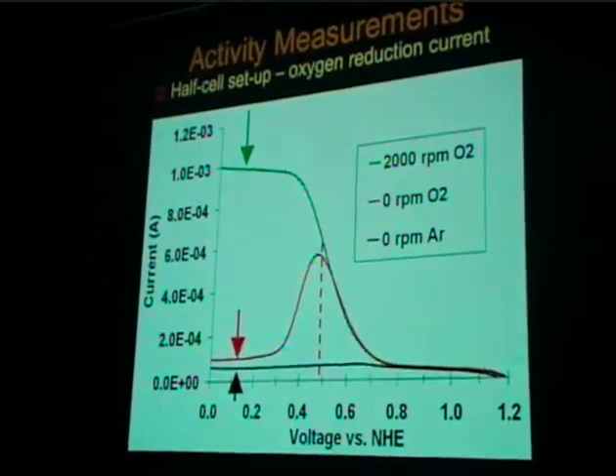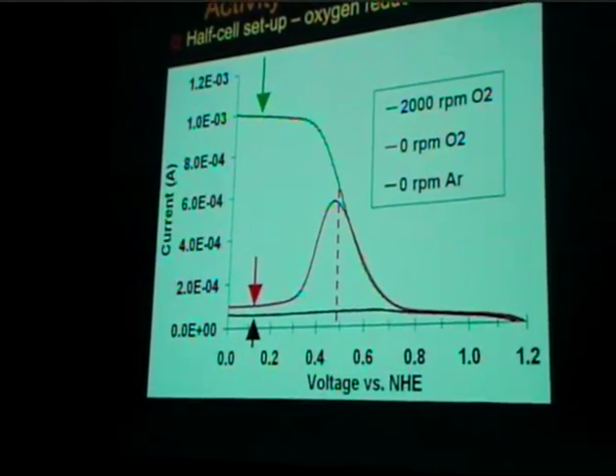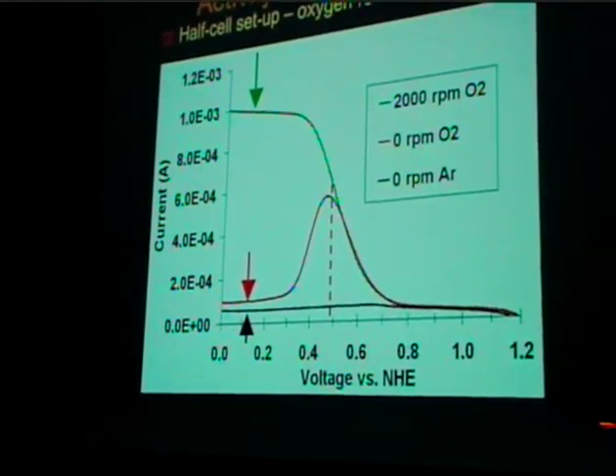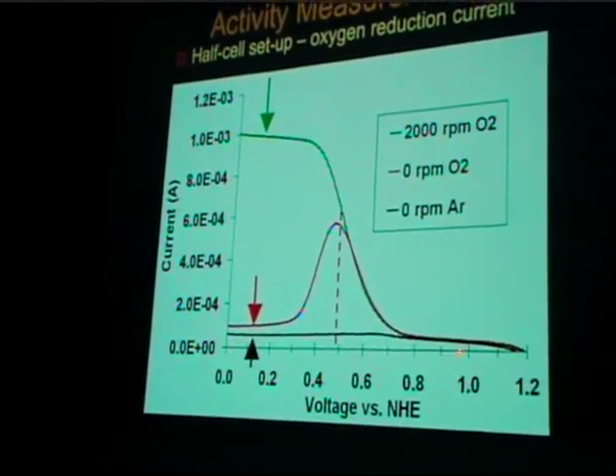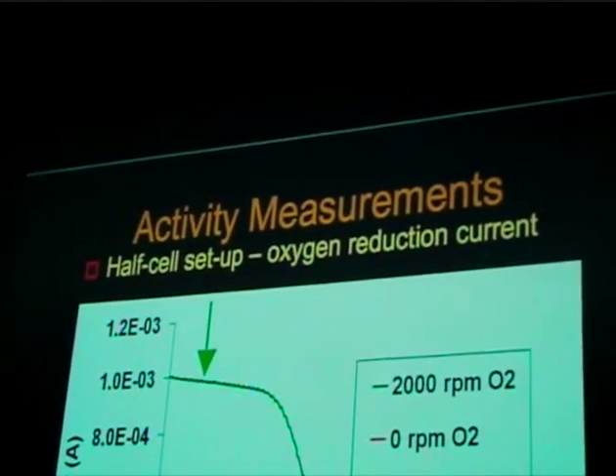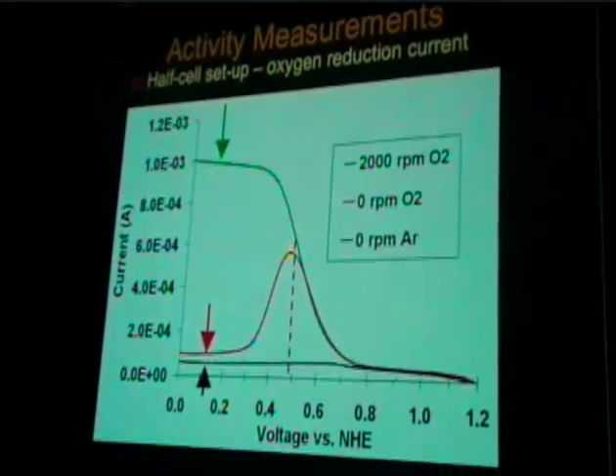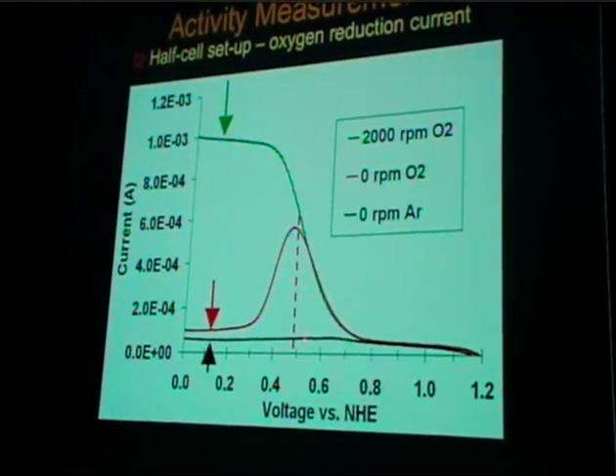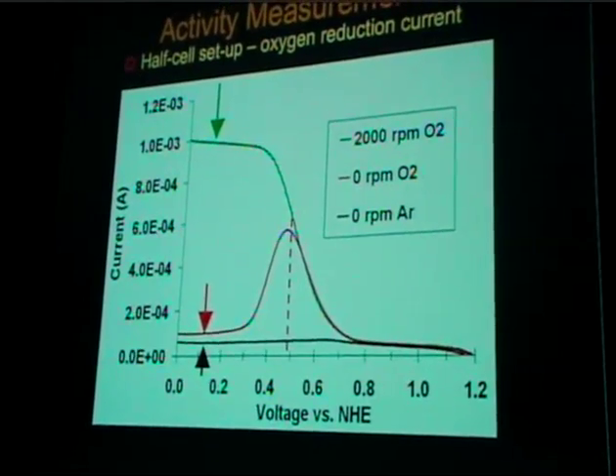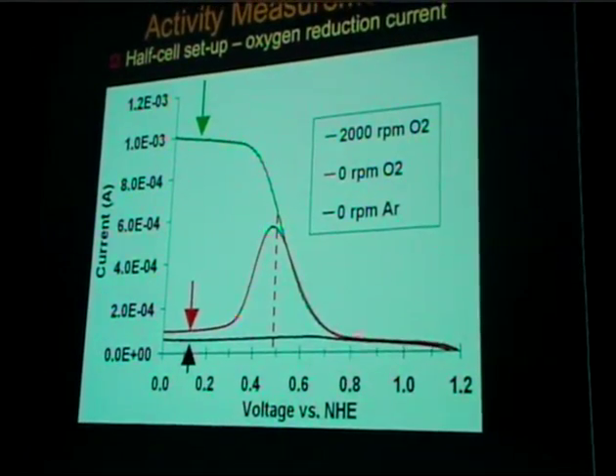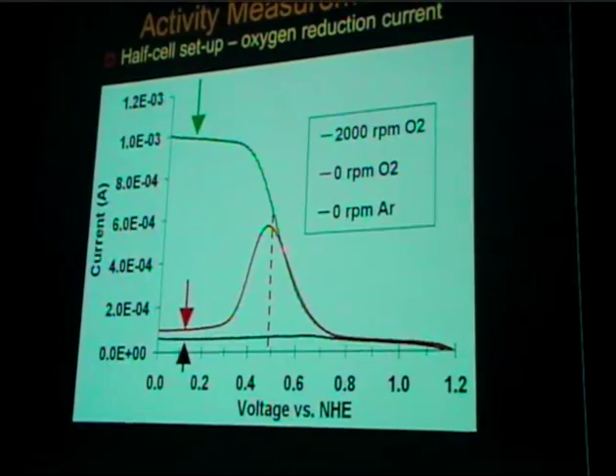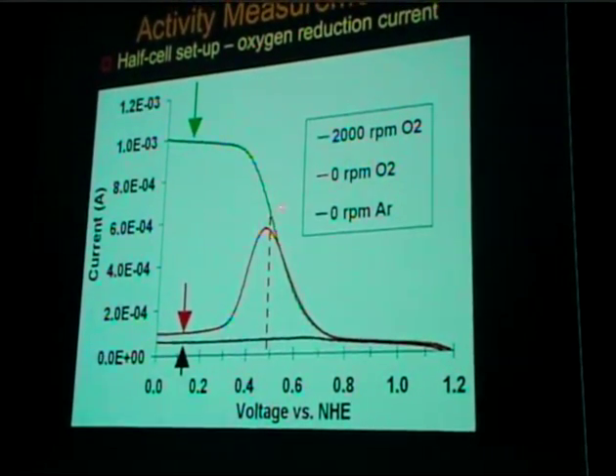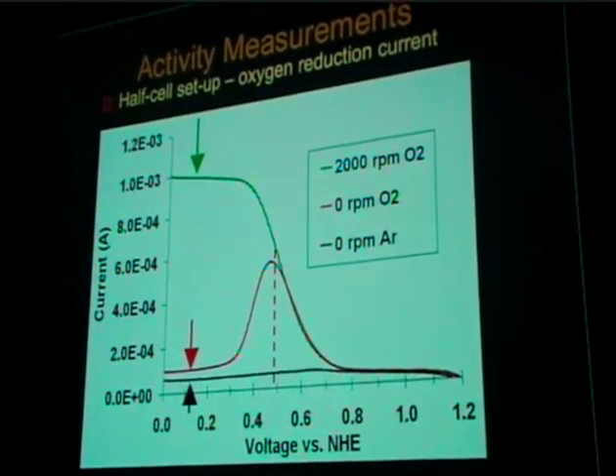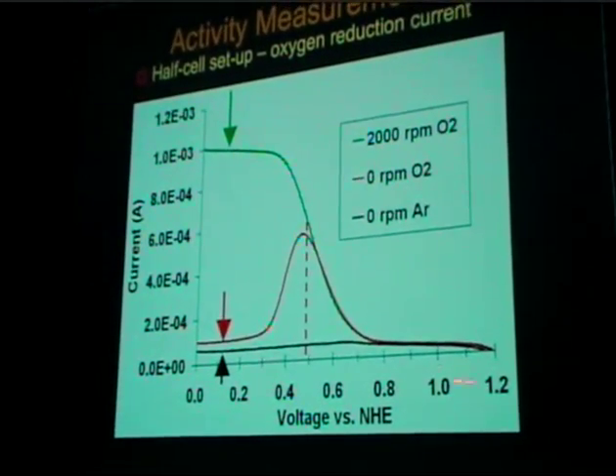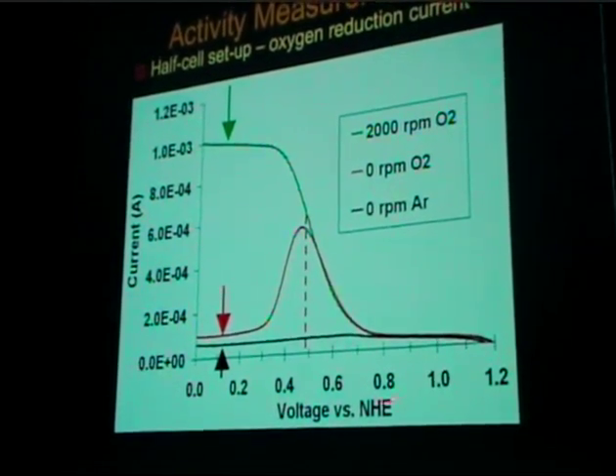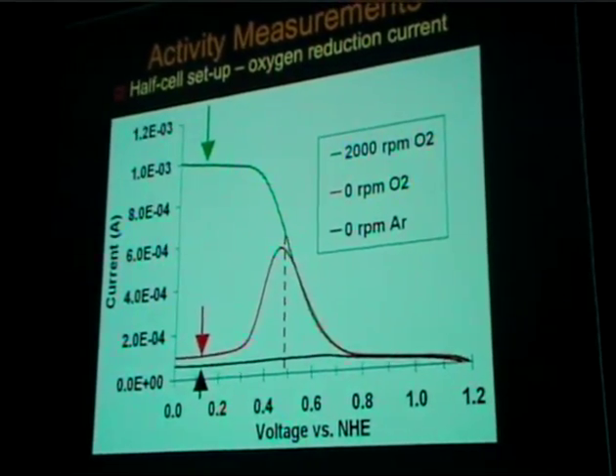Again, if you look at the literature, there are different ways of comparing the activity of these catalysts. Some people look at the voltage at 0 RPM and report the voltage at which the maximum takes place. And some people look at the baseline separation. In our earlier work, we were mostly reporting the position where the peak takes place, and the closer we are to the theoretical value of 1.2 volts, the more active the catalyst.